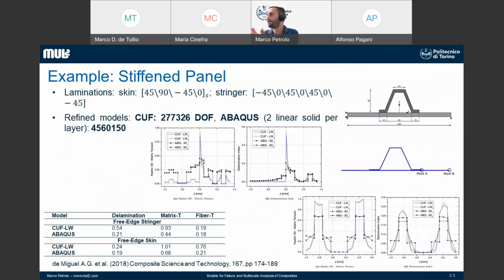For instance, in this example, this is a typical aerospace component in which we have a stringer and a plate. We may have failure, for instance, in this area, because this is again an area in which we have the free edge effects. This is the area in which there is the discontinuity between the plate and the stringer. And you can see this effect in the stress state in these plots here. In particular, in the first two plots, I show you the failure index that was computed via the Hashin 3D criterion. And as you can see, this point is where the free edge is. So in this area here, or point A here, there is a huge increase in the failure index in a very small area. So this is just a numerical example that tells you how important it is to model this kind of structure in a proper way to detect this potentially very dangerous behavior.